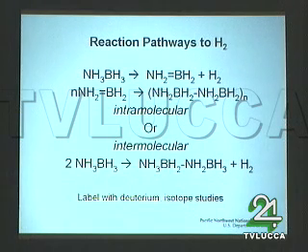So when you start digging through the literature to find out how hydrogen is released from this, there are probably about a half dozen papers, and 5 of those papers say it goes by an intramolecular or unimolecular dissociation reaction, which is a bit surprising because when you first look at this and you have these hydridic and protic hydrogens interacting with each other, you might think it would go by a bimolecular or intermolecular pathway.